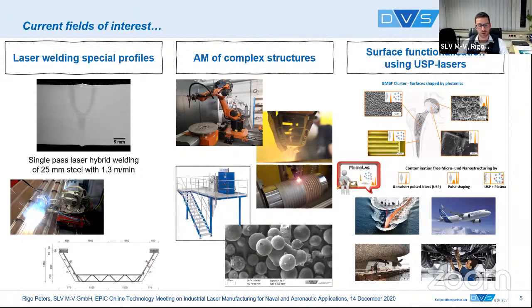One interesting point is that you can use not only static and large systems for this welding. We have also developed, together with partners like Trumpf, Fronius, and other companies, mobile equipment, which you can see on the left side, where we can weld up to 12 or 15 meters of panel length with a mobile tractor equipment, which is fiber coupled to the laser and can be used within the yard.